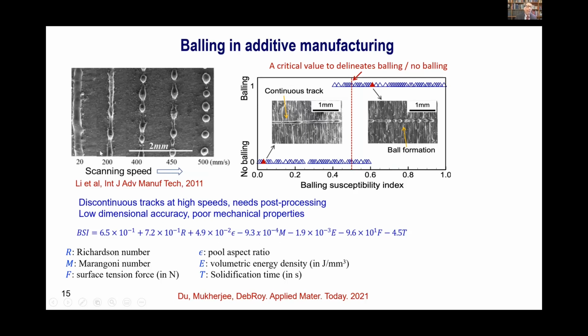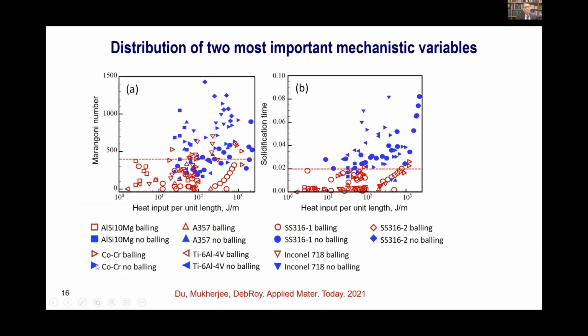If we go very fast in additive manufacturing, sometimes the tracks break up and they form balls like I'm showing here. So again, we use a similar methodology to create a balling susceptibility index, and we verified that by looking at actual data for a large number of alloys that are listed here. So there is a very clear delineation in Marangoni number, which represents the strength of surface tension driven flow, and solidification time, in seconds. These are computed from our heat transfer and fluid flow model. So we can avoid balling using this theory.